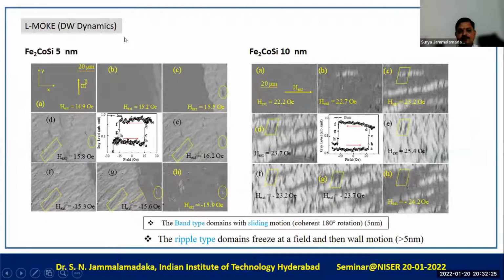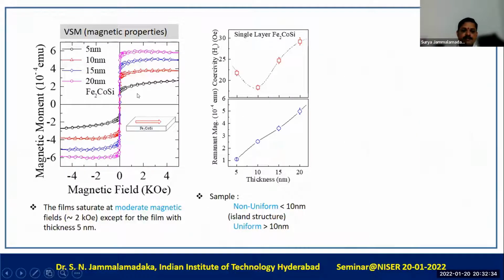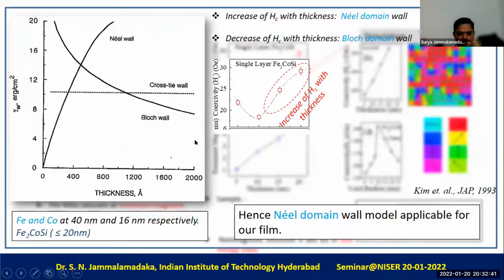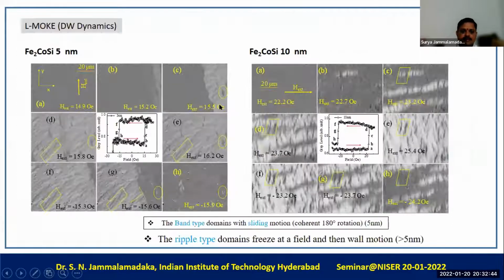And we also tried to do longitudinal MOKE for the domain wall dynamics. As I mentioned, whatever magnetization loops we have obtained are in-plane magnetization loops. For that, we performed longitudinal magneto-optical Kerr effect. So this is the kind of magnetization loop that we have obtained using the LMOKE setup. And we also tried to map the domain images at each and every stage of this magnetization loop.